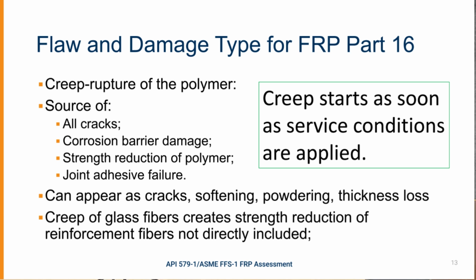The flaw and damage type. Remember I said each part works to a flaw and damage type. For this part, for part 16, the flaw and damage type is creep rupture of the polymer. This is the source of all cracks, all corrosion barrier damage, strength reduction of the polymer, and all joint adhesive failure. Creep starts as soon as service conditions are applied.